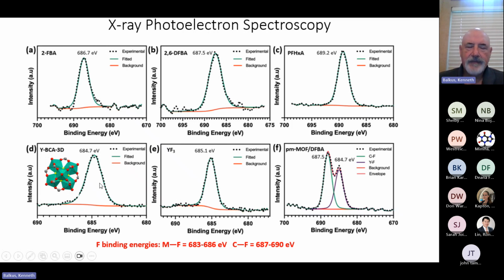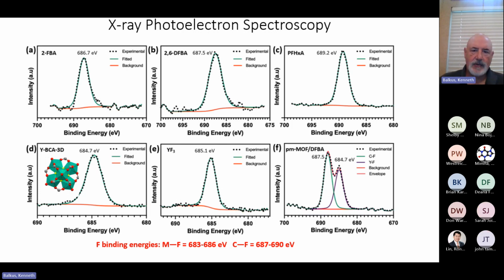Then if you look at the metal organic framework, and this one actually happens to be yttrium, but holmium is the same thing, you see that the binding energy is at 684.7, quite a bit lower than the organofluorine compound. In fact, if you look at just the metal fluoride, it's at 685. Typically we see that for metal fluorine bonds it's 683 to roughly 686, whereas the organofluorines are 687 all the way up to 690, is what we've observed.